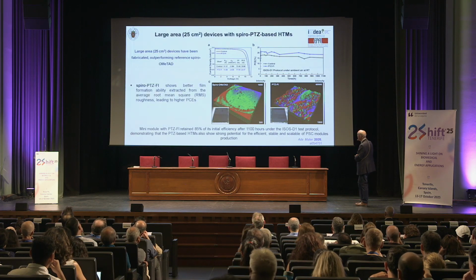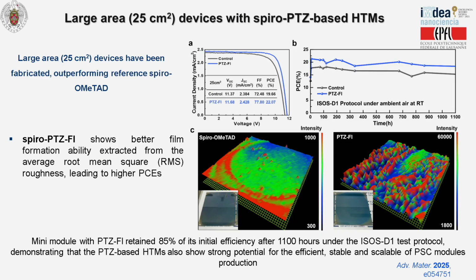And this is the module, the mini module. It was prepared with the spiro and also with the fluorine derivative, and you can see here the behavior of one and the other. In all the studies, the mini module with our compound retained 85% of the initial efficiency after 1,100 hours under these conditions, which are really stringent conditions.